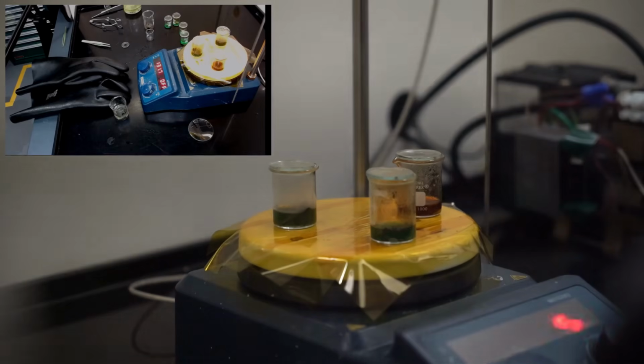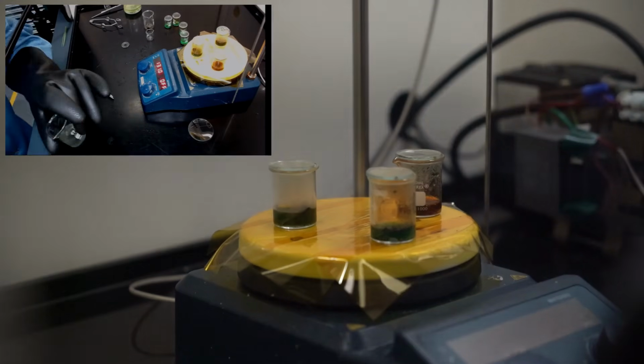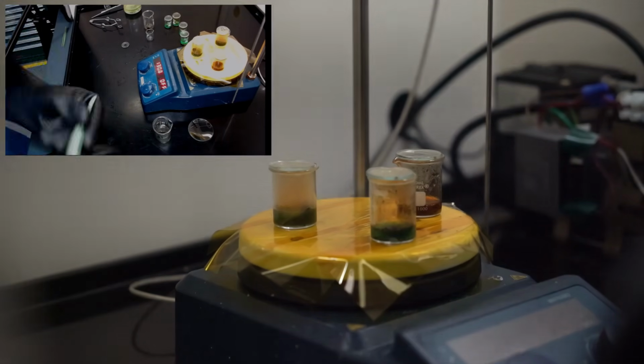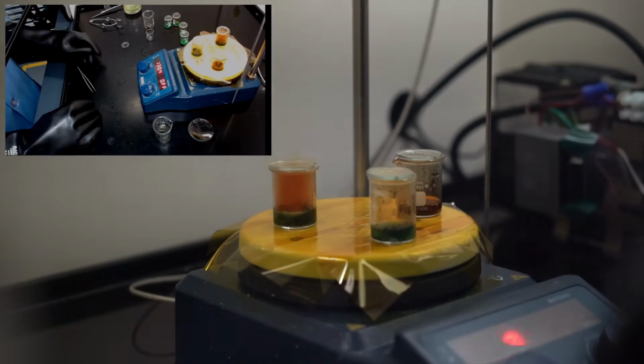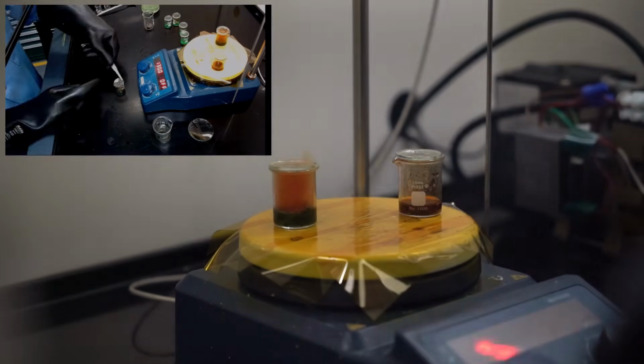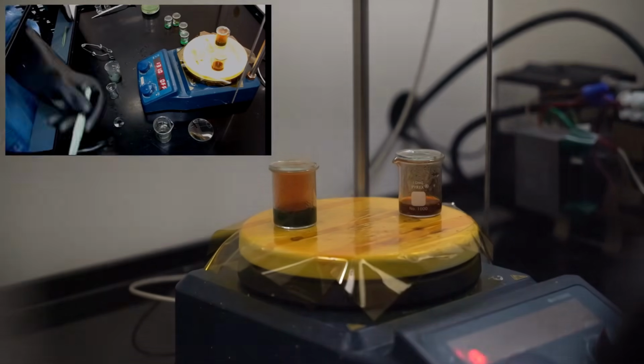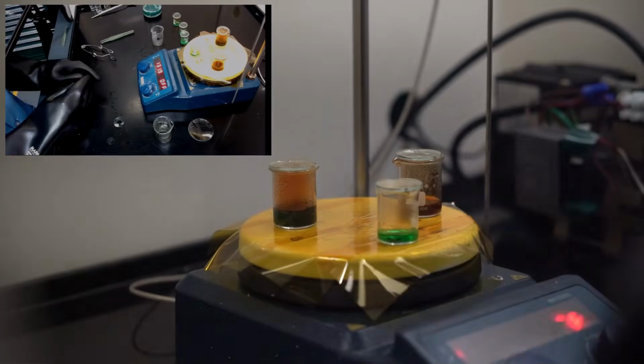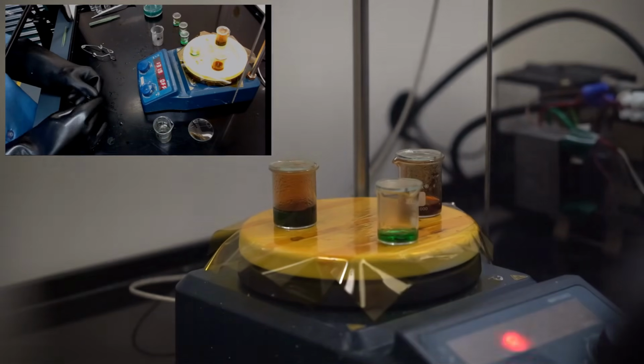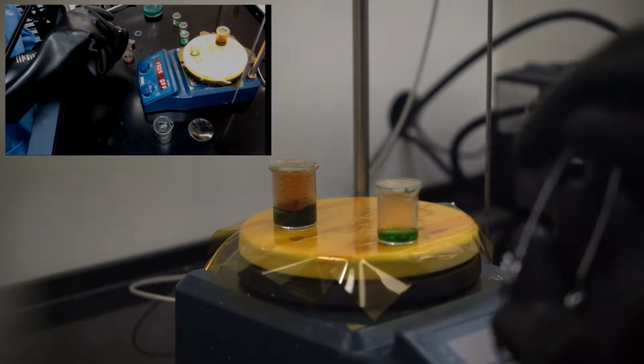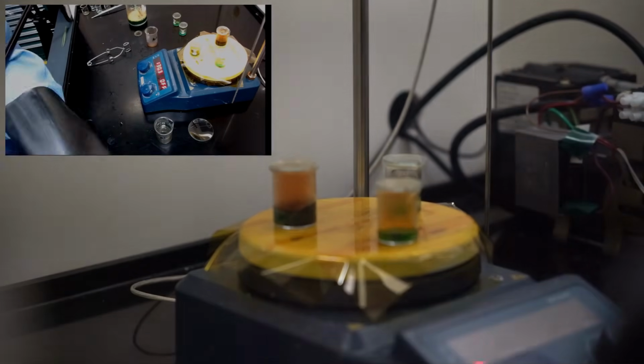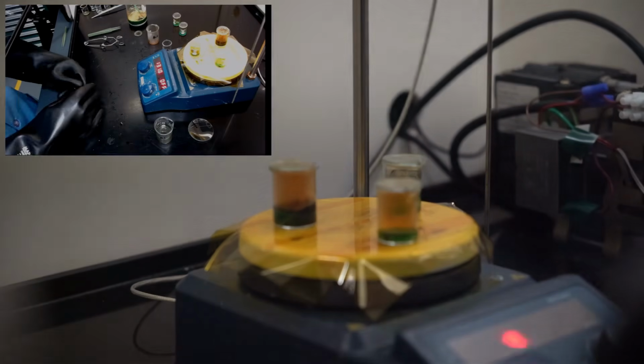So I'm periodically removing some of the big samples to check on them, swishing them around in some acetone to rinse them. You do want to shake off as much acid as possible when doing this so that you don't have too much of a reaction. We don't care about keeping bond wires intact in this case, because we are trying to get bare dies. And as samples finish up, I'll pour the waste acid into an inspection beaker first so that I can decant it back into the original beaker if it needs more time.